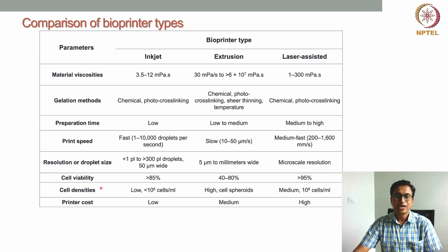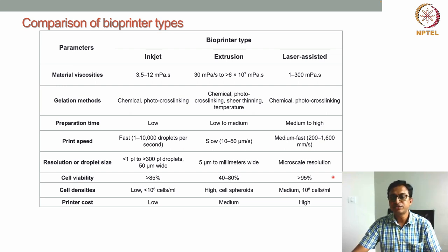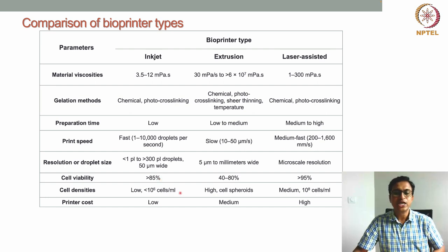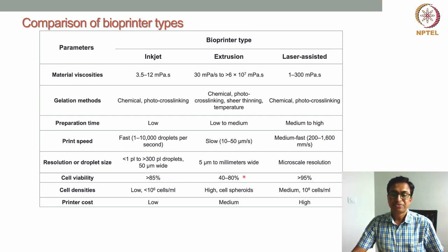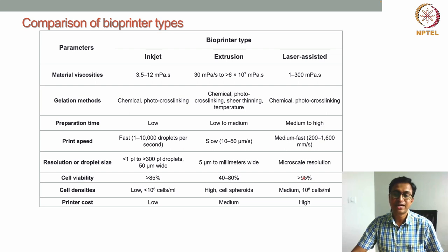Coming to cell viability: both inkjet and laser-assisted are nozzle-free, non-contact approaches, so cell viability is very good. For inkjet, there is some concern about heat generation, but with careful parameter control cell viability can be more than 85%. For laser-assisted, if laser intensity and duration are controlled, cell viability of about 95% is achievable. For extrusion-based bioprinting, the literature reports a wide range — from 40% to 80% viable cells — though with optimized parameters, good cell viability is also possible.